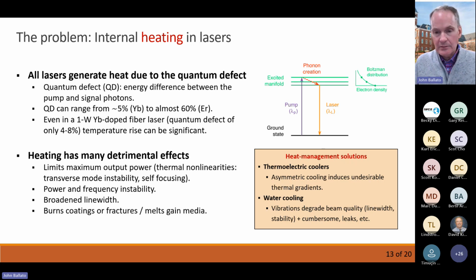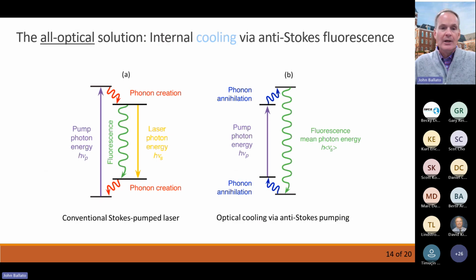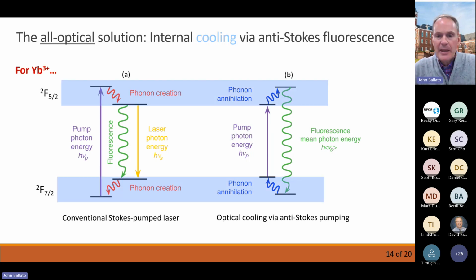Now, normally, to cool a fiber, to cool a laser, you have to either use circulating coolants like water or air, or you use thermoelectrics. But nonetheless, you've got to get rid of this heat, and that adds to the complexity, it adds to the cost, it adds to the weight, it adds to the size. None of those things are good. So there is physics called anti-Stokes fluorescence, where instead of pumping to a higher excited state and letting it relax and getting heat off, what you do instead, say with ytterbium, is you pump from the bottom of the ground state to the top.